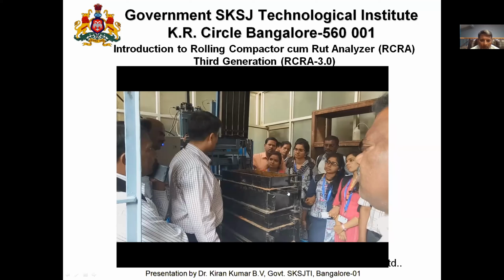Surface water can be added to simulate the rain condition, and we run the accelerated rutting test. Now there are 2 components one should understand in this research. One is to fix the optimum dosage of the bitumen content, for which we are using this roller compactor. Once that is done, we construct the complete pavement component. Using the optimum binder content designed with this roller compactor, a slab is cast, and then we measure the rutting potential of that pavement at various temperatures and various tire pressures. If 10 kg per square centimeter comes due to overloading, what is the effect? If it is 60 degrees, whether that binder can sustain more repetitions.